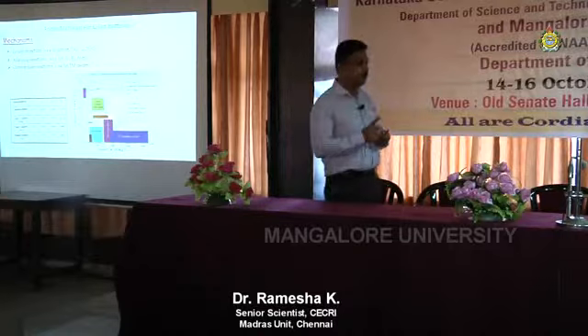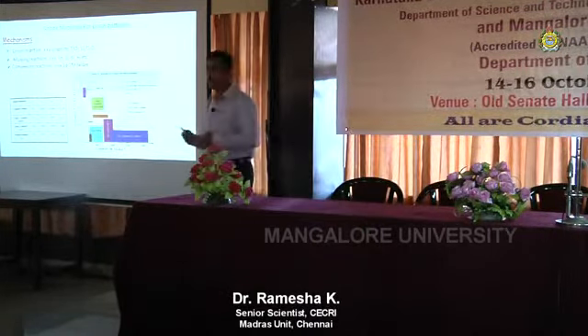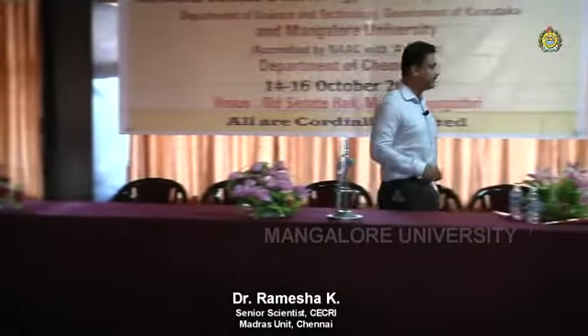I told you that we coat this material on the copper sheet or copper ribbon. When this volume change happens during charge and discharge, the interparticle contact is lost as particles shrink, expand, and shrink back. The particle or the area peels off. This is the real problem, and the battery fails there. So if you use silicon or tin material, after a few cycles your electrode material peels off because of the volume changes and stress developed in the crystal structure. Even though they show good capacity, like this 4000 compared to 200, silicon, tin, and aluminum will fail in a battery because of the volume change.